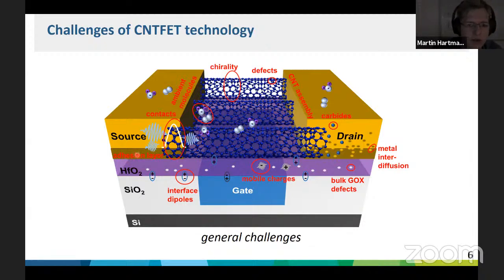And then you need to consider the interaction between the contact material and the adhesion layer. You might get some metal interdiffusion, some alloys forming. This changes the work function of the material. And then you get a different barrier here at the contact sites. Okay. Another important aspect is that you need to remove all the residual molecules here at the contact site and also on the CNTs in order to get an ideal contact.